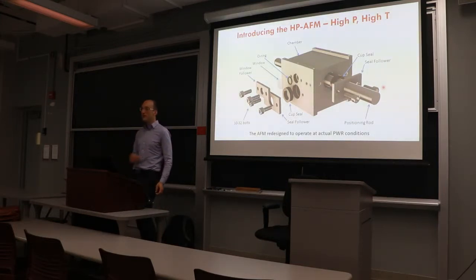If you add the pump down and venting and reloading time, it's an hour per batch. And so at 24 rods per hour, running 24/7, 365 days a year, you need one machine to coat the US supply of rods every year. Now, note the fact that you don't have to coat every rod. You only have to coat the 10 or 20% hottest rods. And you don't have to coat the whole rod. You just have to coat the hot spans, maybe the 2 meters with the most boiling. And then all of a sudden, you've got capacity to spare.